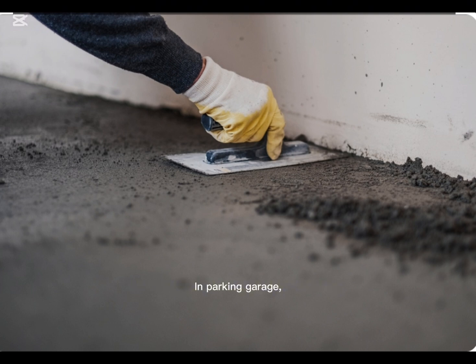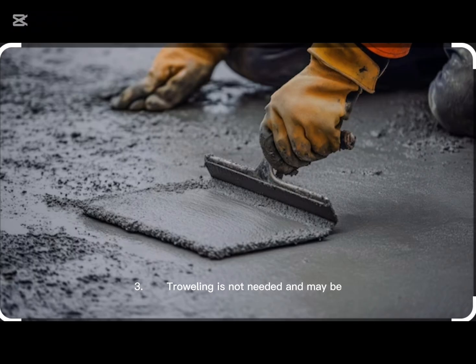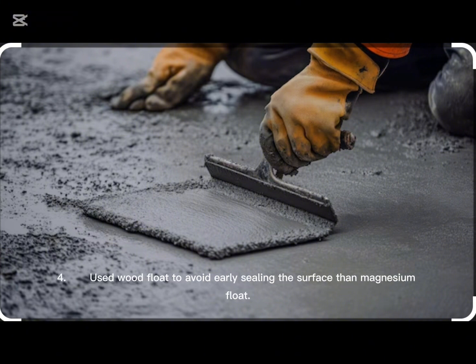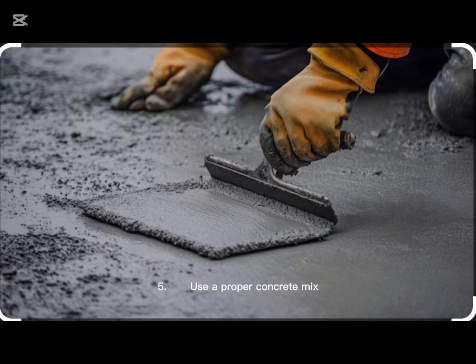In parking garages, parking lots, and sidewalks, floating and brooming or floating only are the best finishing methods. 3. Troweling is not needed and may be harmful to scaling resistance of the surface. Troweling air-entrained concrete may also cause delamination. 4. Use a wood float to avoid early sealing of the surface than a magnesium float. 5. Use a proper concrete mix with durable and well-graded aggregates and a low water cementitious ratio.